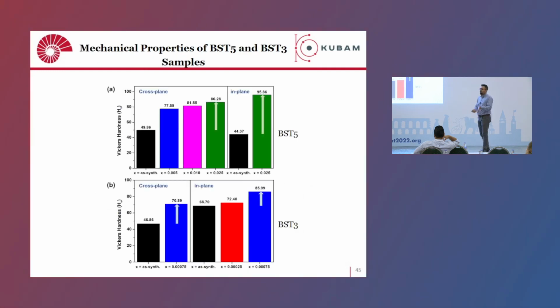In addition to the transport characteristics, it is better to also check the microhardness, or the mechanical properties of these materials, because when you do module applications, we want durable materials. Here you can see the synthesized materials, which are black. This is bismuth 0.5, and this is bismuth 0.3. When we add copper telluride, in both the cross-plane and in-plane directions, we see a substantial increase in the microhardness, the mechanical properties of this material.